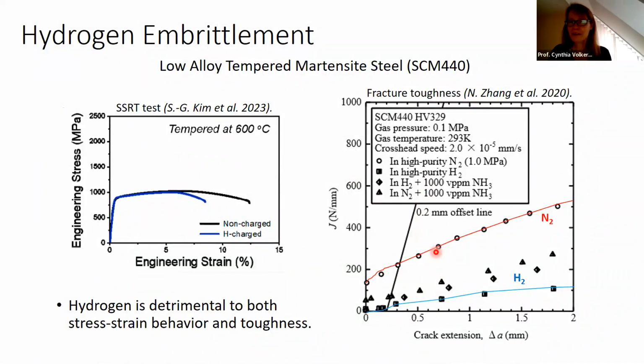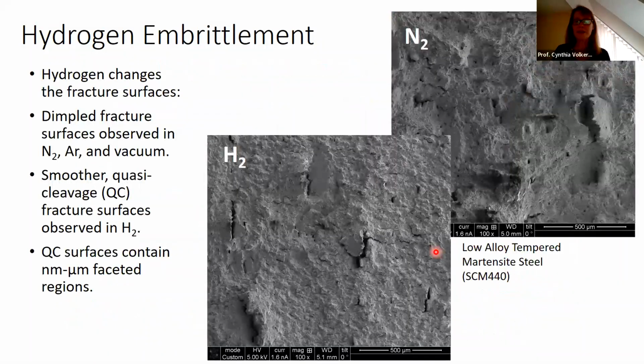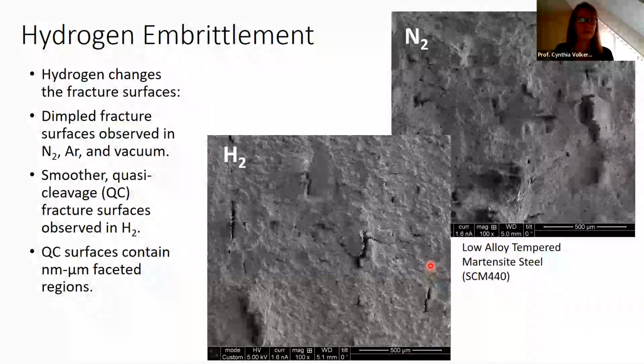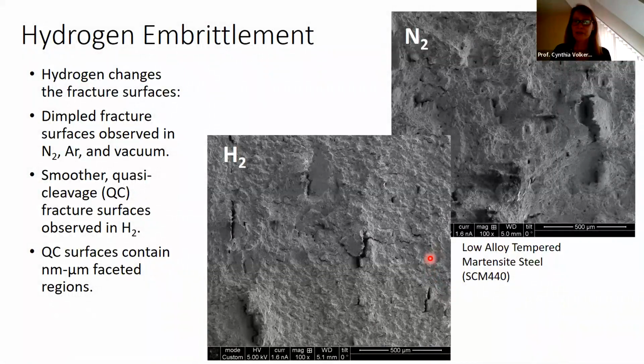And of course, one wants to understand why hydrogen has this effect, and one does things like look at the fracture surfaces. And here you see images of fracture surfaces for samples that have been fractured in nitrogen or in hydrogen. And you can see that they're quite distinct, quite different. I'll show a higher magnification in a moment, but generally at this large magnification, this scale bar here is 500 microns, which is half of a millimeter. So this is quite a large scale, and you can see that the hydrogen surfaces are flatter, with fewer features on the surface.